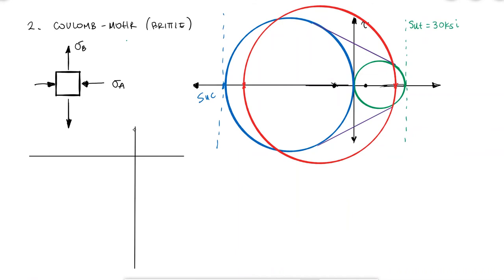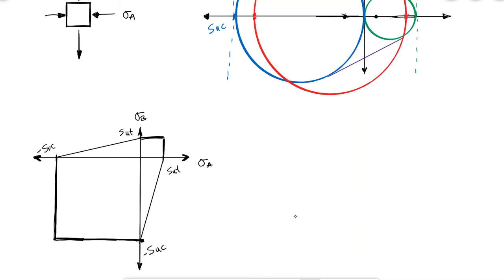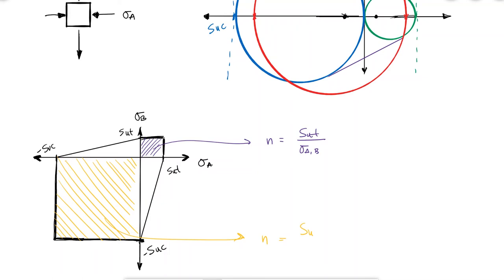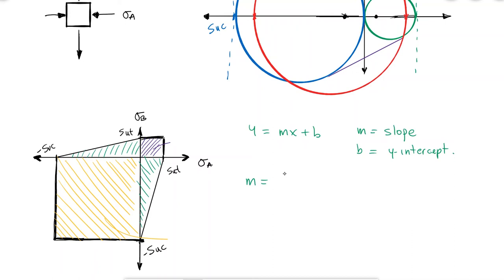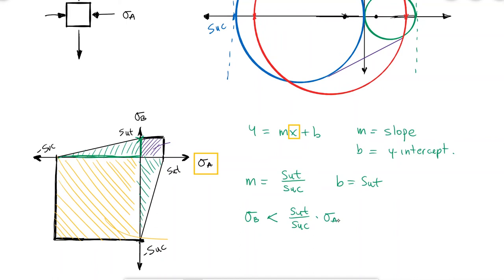This is represented in the stress envelope as a diagonal line in the second and fourth quadrants — the quadrants corresponding to case 2 of Mohr's circle. The factor of safety is still defined as the ultimate strength over the maximum stress if both principal stresses are positive, or the ultimate compressive strength over the magnitude of the largest negative stress if both are negative. In the case where one is negative and the other positive, we use the equation of a straight line: the slope (rise over run) is SUT over SUC, and the y-intercept is SUT. Since σB should not be greater than the value given by that line, dividing by SUT gives us: σB/SUT minus σA/SUC should not be greater than 1. Therefore, the factor of safety can be calculated as 1 over the difference of those fractions.